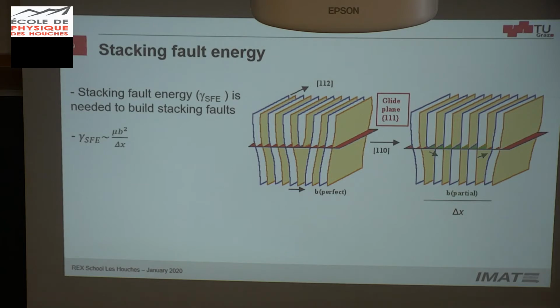So it means, I'm going to recall everything. It means that if the stacking fault energy is very high, this is very small, these partial dislocations are not forming, are not stable. The dislocations will move, and you will have dynamic recovery instead of dynamic recrystallization. In the case of nickel-based alloys, for example, where this stacking fault energy is very low, stacking faults are forming, stacking faults, twins, all this. Even more weird stuff than stacking faults only. And this will avoid the movement of dislocations, and therefore it will be prone to dynamic recrystallization instead of dynamic recovery.